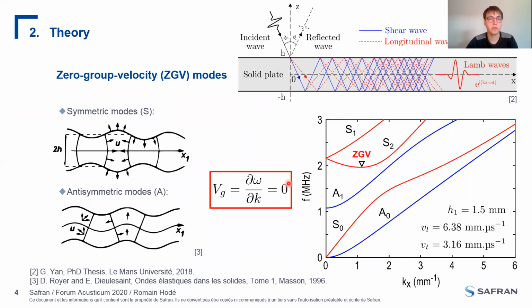So now, concerning the theory about ZGV modes, if you consider a plate here, you will have the reflection of transverse and longitudinal waves at both free surfaces. And this multi-reflection leads to Lamb modes, which are symmetric or antisymmetric modes. And you can represent these modes on this diagram as a function of the frequency and the wave number. And you can plot the dispersion curves, in red and in blue. And you can observe that at this point, the slope of the curve is equal to 0. So this means that the group velocity is also equal to 0. And we will have a ZGV resonance at this point for this specific frequency and this specific wave number.